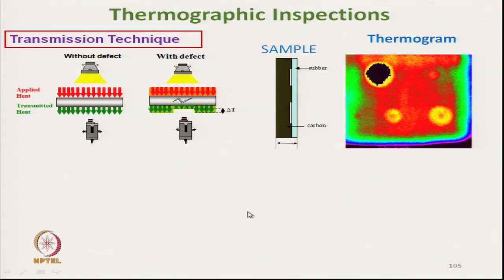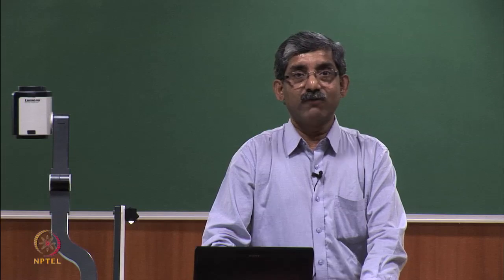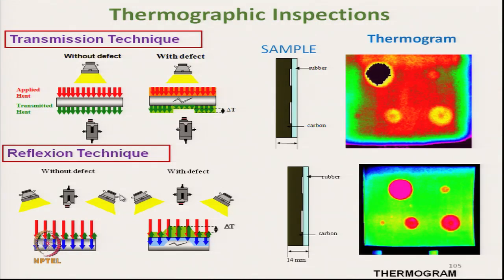Now this method works in the reflection mode, where the heat source and the camera are in the same direction. On the left side it is showing the specimen without any defect, that means the reflection of heat is uniform. But on the other hand, with a defect present here, the heat reflected will be totally different in the defective zone than in the normal zone.